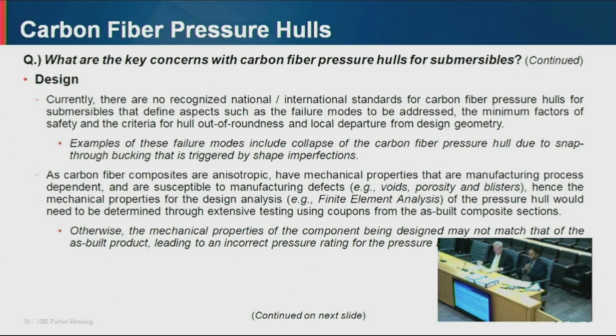This is a little different from traditional pressure hull materials, because when we do the design review of traditional pressure hull materials, the material allowables and the mechanical properties come from the material specifications, okay? You typically do not use the as-tested mechanical properties because they may exceed the material allowables. If they don't exceed, the material is rejected, okay? But the as-tested properties are typically not used when you design pressure hulls made of steel or titanium, because the properties you use there come from the material specification. Those define the minimum acceptable properties.